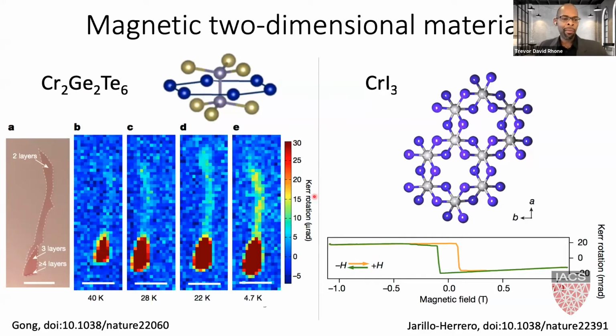came out of this. So this view graph on the left shows MOKE measurements, which essentially measure magnetization, and it shows that there's a 2D map of chromium germanium telluride down to two monolayers, and that has signatures of magnetization below the Curie temperature. And on the right side, we have this hysteresis curve of this chromium triiodide showing down to one layer, we have a magnetic ordering.